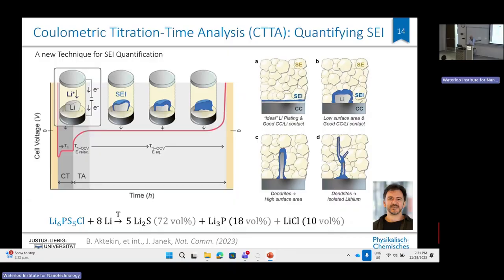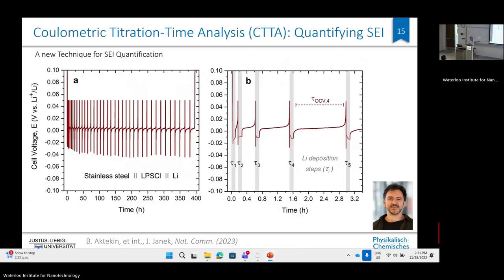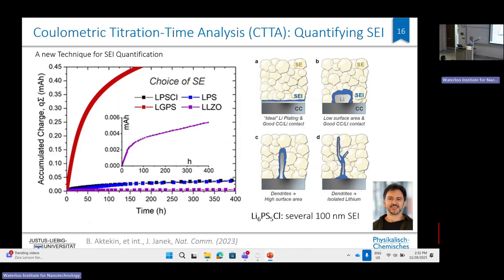If all lithium is consumed and no lithium is here, the voltage will fade quickly. That has reasons, and it will reach a rather high positive value. And you then simply measure the time for the consumption. You make that in several steps. Each step looks the same: nucleation, plating, consumption, and you see that it gets longer and longer. What in principle happens is that you form this layer, and the growth takes longer and longer, because it's a diffusion-controlled process. In fact, these curves for charge being consumed by the SEI over time mostly show simple parabolic time behavior, as defined by simple diffusion across the SEI.